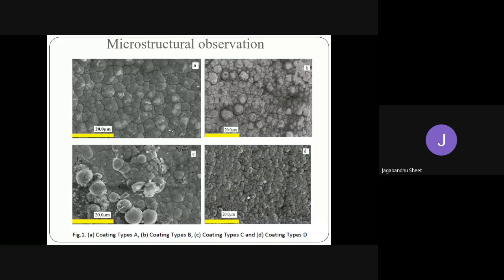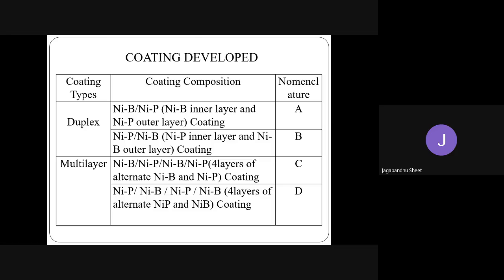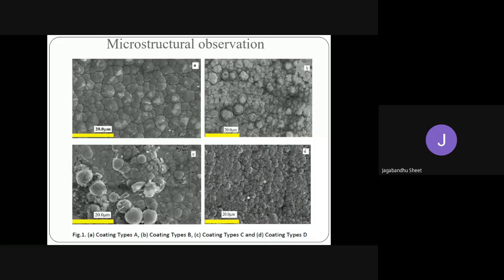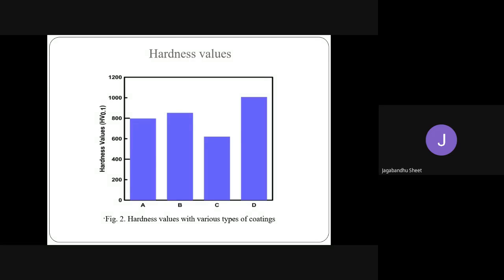A, B, C, D are the different types of coatings. With the NIB as the outer layer, as in coating B, and NIP as the inner layer, we can see a simple cauliflower type of phase, and different hardness values are measured. For the multi-layer coating D, when the NIB is the outer layer, a very high hardness value is found, above 1000.